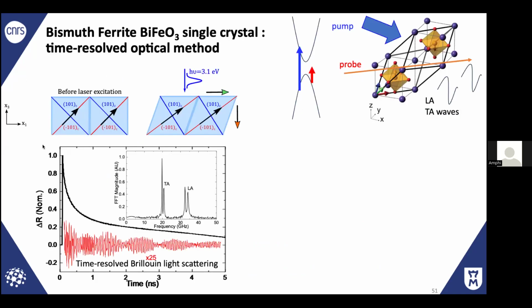So this is what we did in bismuth iron oxide. When we shine light, since there is a polarization, this indicates that the system is non-centrosymmetric. So the force you induce with the light is not isotropic. So there is shear as well as the longitudinal. And when we look at the pump-probe experiment, you excite the system and look at how the transient reflectivity changes as a function of time. If you make a Fourier transform, you immediately see these two components, longitudinal and transverse.